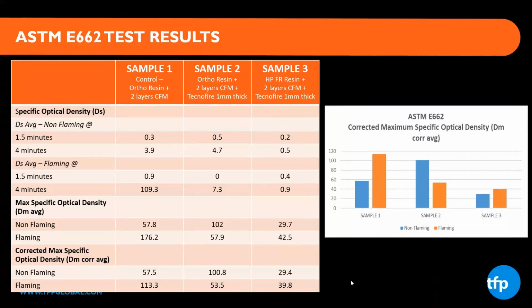And once this was set alight, the flaming version, the blank was at 109.3, and we reduced that down to 0.9. So an incredible change from going from the blank sample to the systems approach. The corrected max specific optical density chart is on the right. The corrected just means that they take into account any solids that have deposited on the optical lens. So you can see the results between the non-flaming and flaming and how much of a reduction we saw.